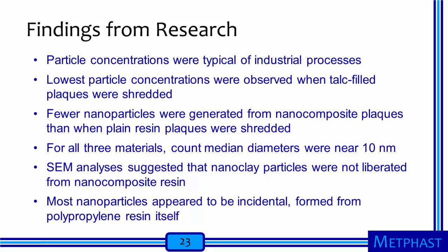Scanning electron microscopy images suggest that the nanoclay was not liberated from the nanocomposite plastic. Instead, most of the nanoparticles appear to be formed from the polypropylene resin itself, perhaps by condensation of polymer vapors produced by heat when the test plaques were shredded. This hypothesis for particle formation requires further investigation.